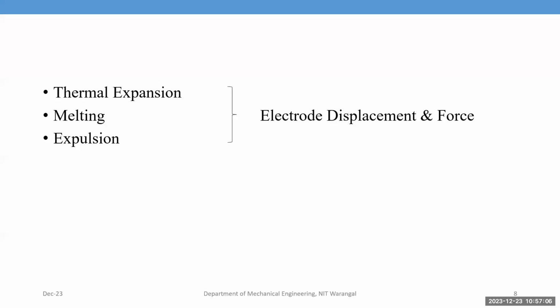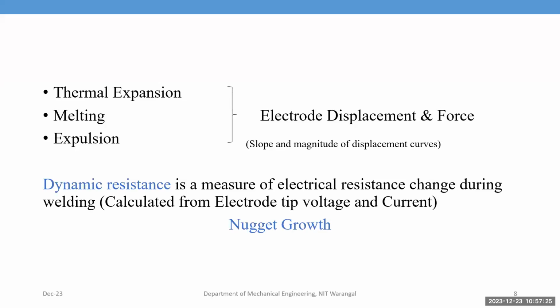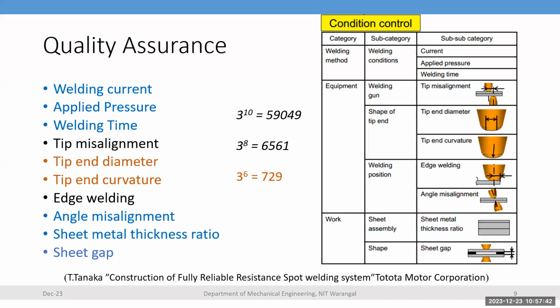Then, apart from that, heat is accumulated over a period of time, causing expansion of the material, because the material has electrical conductivity and thermal conductivity. Then expansion takes place, then melting and expulsion because of the electrode displacement and force. Dynamic resistance is a measure of electrical resistance change during welding, calculated from electrode tip voltage and current. That depends on the voltage and current you supply, so you can also get the dynamic resistance. This is the basic information about the process.